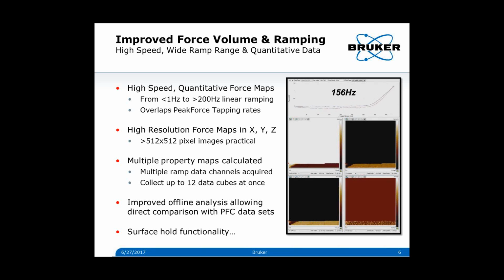So this is, I showed you, when I was showing you the 1 hertz, that was a 16 by 16. I increased the resolution on this to 128 by 128. Now you notice that the force is a bit higher on the high frequency. That's caused by overshoots. Now that would not be an issue with peak force tapping, but with very high rates in force volume, you will start to see some overshoot because it's trying to trigger on each individual curve. At least we've eliminated the ringing though.